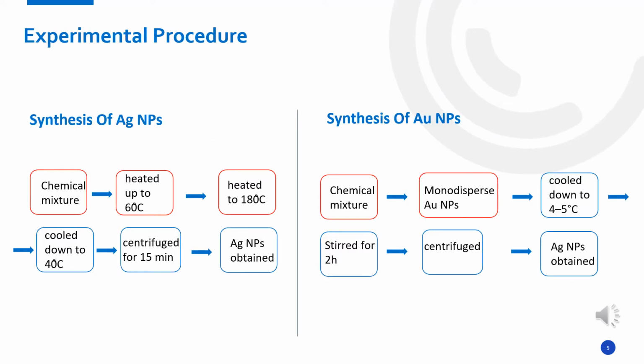For the experimental procedure, we will see how to synthesize Ag and Au nanoparticles and how to prepare the solar cells. For the synthesis of Ag nanoparticles, chemicals are mixed and stirred at 700 rounds per minute under continuous nitrogen flow. Then, this mixture is heated up to 60 Celsius slowly and kept at this temperature for 5 minutes. Next, the resultant mixture is heated to 180 Celsius and kept at this temperature for 20 minutes. After that, the solution is cooled down to 40 Celsius and this mixture is centrifuged for 15 minutes after adding isopropanol. Then the nanoparticles were separated in the centrifuge tube, so Ag nanoparticles will be obtained finally.